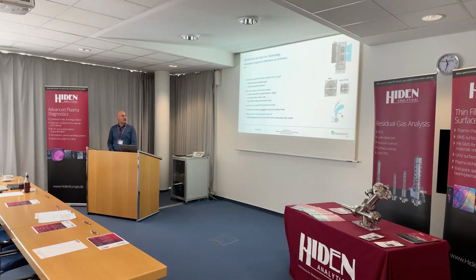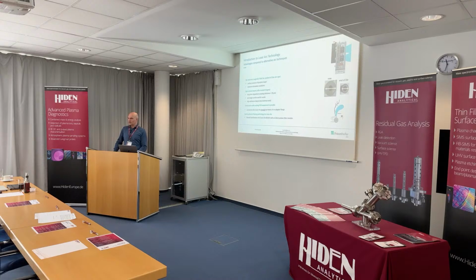What are the advantages of our technology? We don't need magnetic fields for control of the arc spot. Otherwise, if you use a DC arc, you have a magnetic field generator or magnets on the backside, maybe adjustable also, to get a good utilization of your cathode. In our case, we don't need this anymore. And as you see on the right side, we have a new and an end-of-life graphite cathode, and we can utilize nearly all of the material because we can scan and use all areas of the cathode the same.